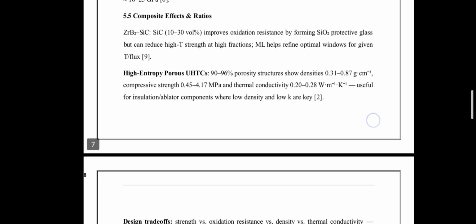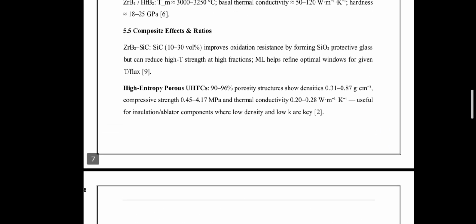Now we will see the composite effect and their design. Composite optimization: in zirconium boride silicon carbide composite, silicon carbide addition of 10 to 30% volume improves the oxidation resistance by forming a protective silica oxide glass scale. However, excessive silicon carbide can degrade the high temperature strength. Machine learning approaches are increasingly used to identify the optimal composition window for specific thermal and flux conditions.